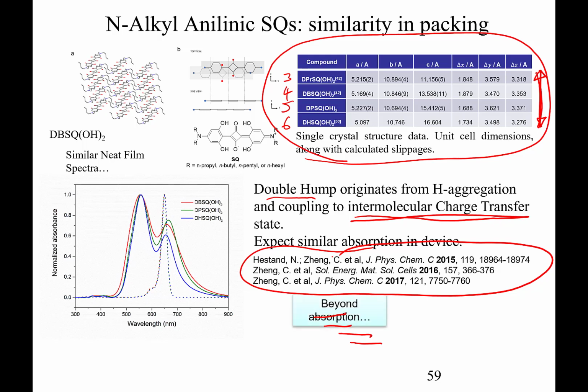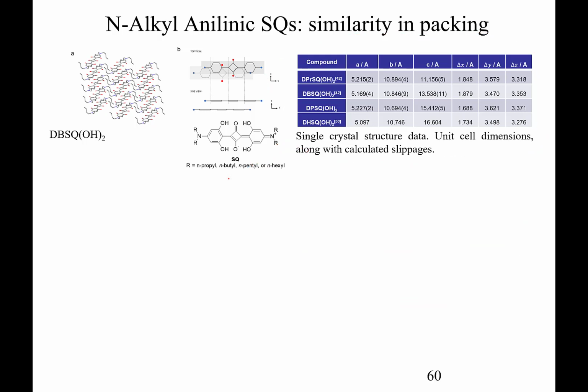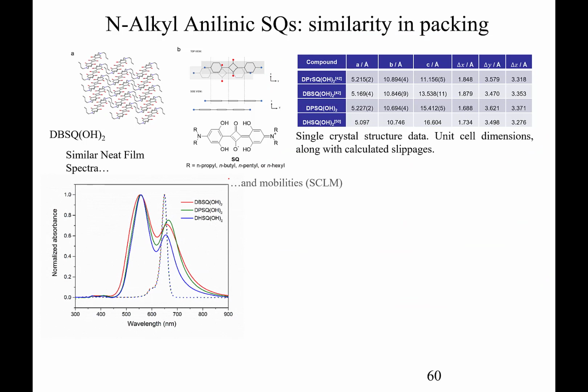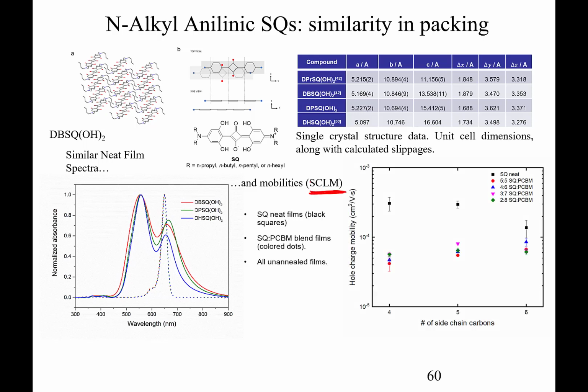But we know that when these materials pack in the same way, we always see this double hump spectrum. So these are 3 of those materials from the table. And we recognize that the spectra are pretty much the same. So beyond the absorbance, what else can we think about in terms of how these devices operate? So we've actually done some space charge limited mobility measurements. And what we found also is that as the number of carbons in the side chain increases from 4 to 5 to 6, in neat Squaraine, the mobility doesn't really change much. In fact, it does decrease for the hexyl.